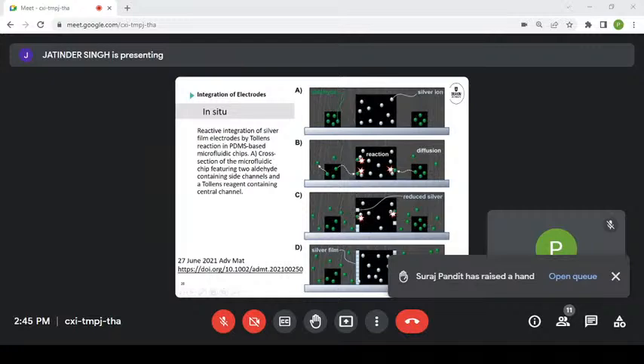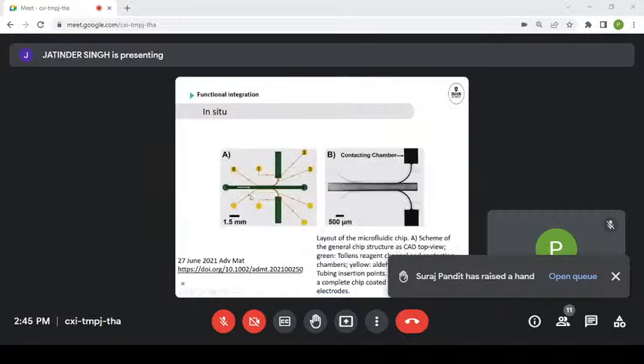We get a reduced silver electrode being formed, and on the next slide you can see that a little bit nicer, where we can see the different reagent channels, and we can see that the silver electrode is being formed at the boundary where these channels are. So after the removal of the reagents, we can still see that we've got a silver electrode left that's integrated into a microfluidic device. Again, very easy to do, because once we've got a microfluidic structure, we are very good dealing with fluids. We're not that good dealing with solids. If we can make our solid electrode out of liquid reagents, that makes life a whole lot easier.